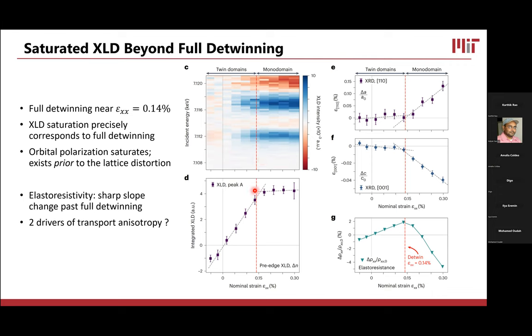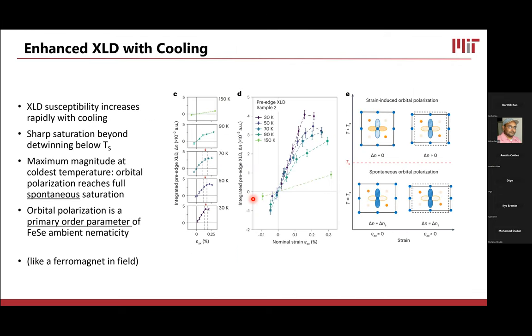Okay, so we did this really careful study at a single temperature. What does this look like at different temperatures? All of this data is represented in these boxes here. We basically went to a single temperature and we changed the strain state from lightly compressive up to maximum tension, and we looked at the change in the XLD. So 150 Kelvin is 60 Kelvin above the transition, and we see that even by applying a very large amount of strain, we can't induce a very large XLD signal. As we cool down and hit the actual nematic transition at 90 Kelvin, we can apply strain and get a medium value of the XLD signal. So we're able to get some orbital polarization, but only after we apply a large amount of strain.